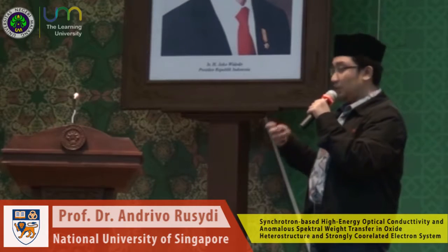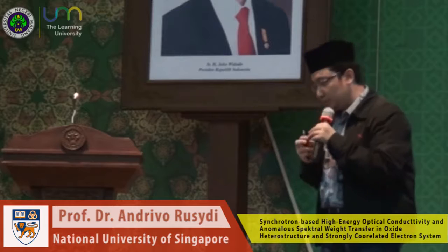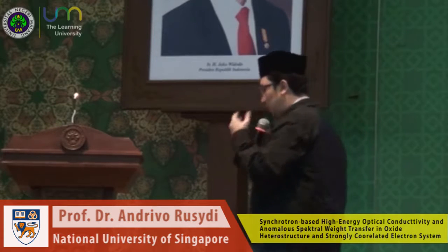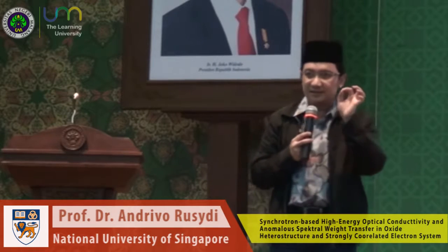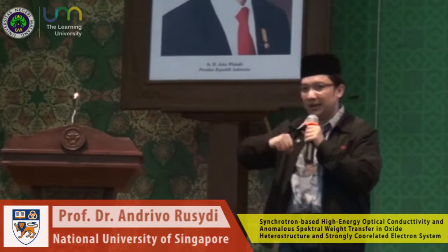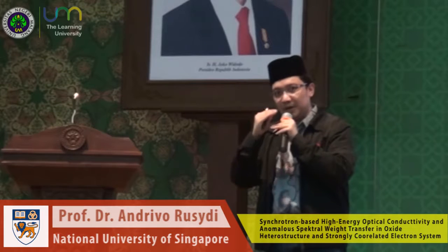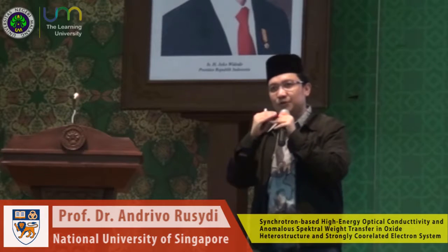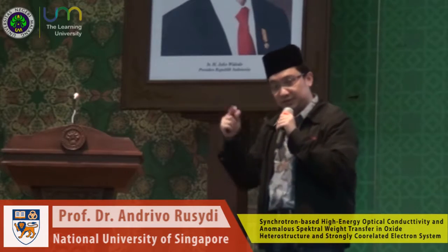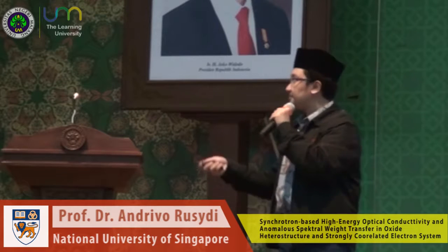So we grow the films. We do what we call pulsed laser deposition. You really hit the target with the laser, and some plume comes out, and then you get atom by atom on the substrate, and you characterize that as a function of thickness. There are fringes coming out from your reflection pattern.